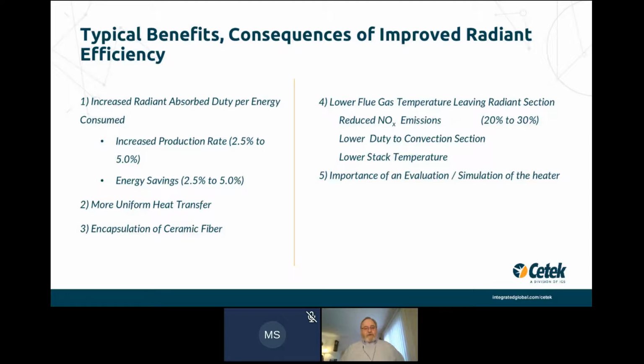Because we're absorbing more heat in the radiant section, the bridge wall temperature and the flue gas temperatures are lower. Also, the NOx emissions, which are related to flue gas temperatures, are also reduced. And we typically find, or our customers report to us, that after coating an SMR unit, we get something like 20 to 30% reduction in NOx emission. A few of our customers have applied coatings just to get the NOx emission reduction. The duty is lower to the convection section, and again, it's important to do an evaluation because of that.